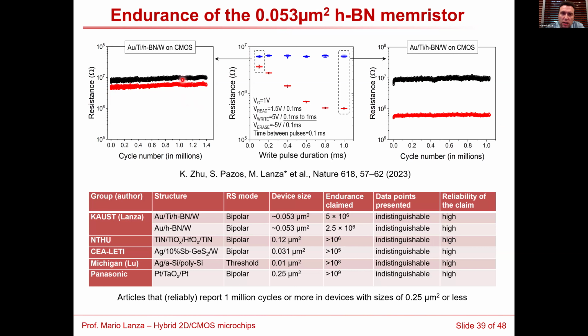Here, you can see that we can also adjust the on-off ratio in different ways. Here, I show you the plot for adjusting the on-off ratio by changing the duration of the write pulse. But you can also adjust it by changing the switching voltage. And we compare with the works in the literature, and we found very few studies in small devices that show high endurance. Very few. And this is one of them.